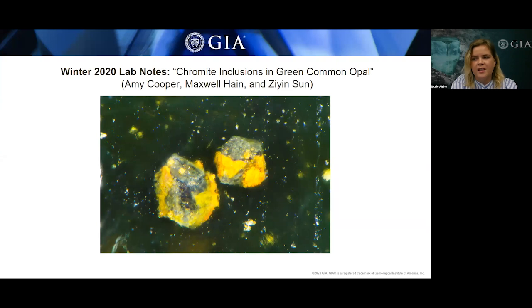Internally, this opal housed several small, well-formed black opaque octahedral inclusions with some yellow staining. With the use of advanced testing, Raman and laser ablation inductively coupled plasma mass spectrometry, which I will call ICP-MS for the rest of these presentations, the inclusions were identified to be chromite, with chromium being the coloring agent for this common opal.